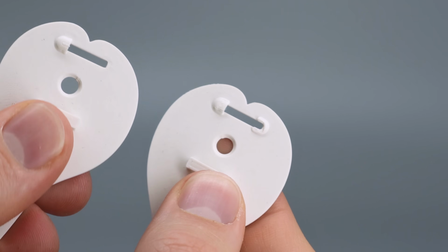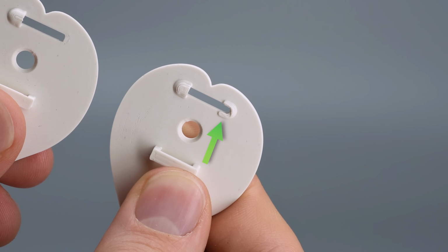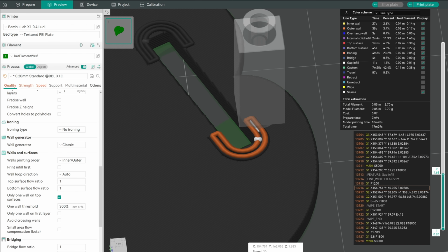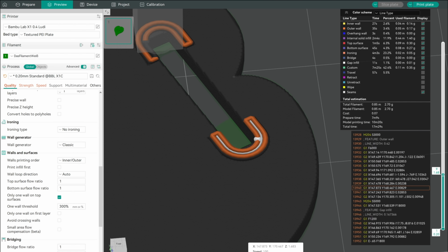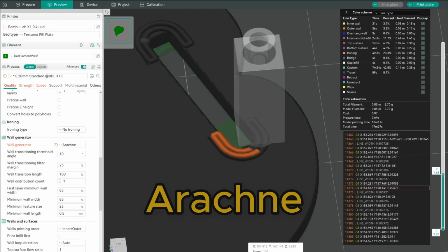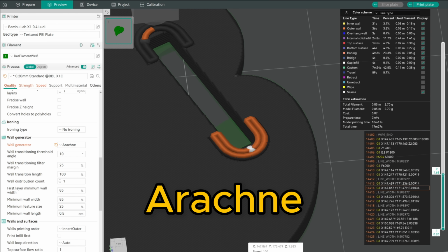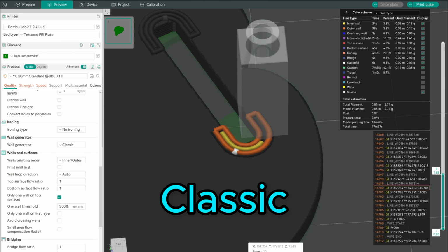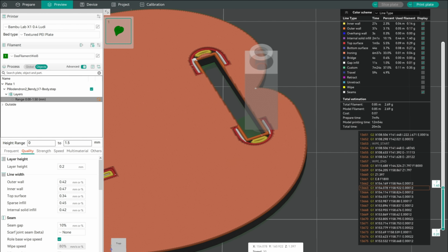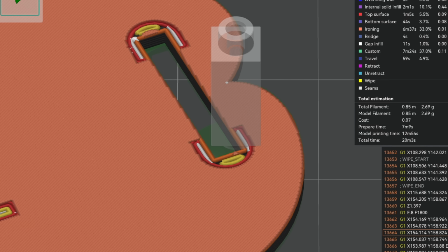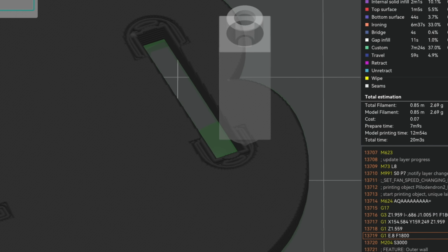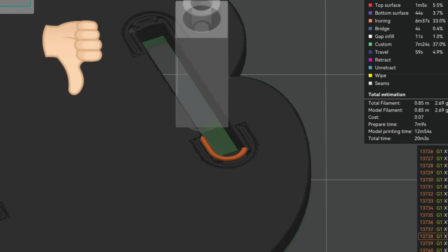With that done, it would now sometimes still break two layers above, like shown here. And sure enough, this section contains one of those incredibly thin lines. We could use the arachne wall generator, but I also designed this part just a tiny bit wider, so now even classic mode prints a thick line. The last little detail we overlooked is at the end of the ironing layer. It's those sneaky little extrusions again. After those, the next layer starts with our problem section.